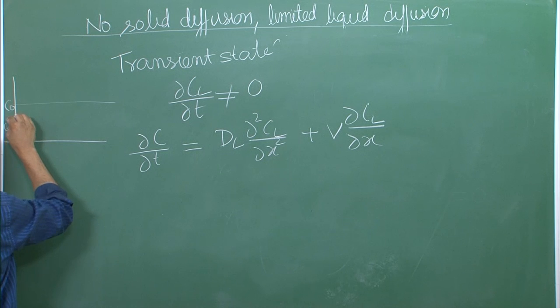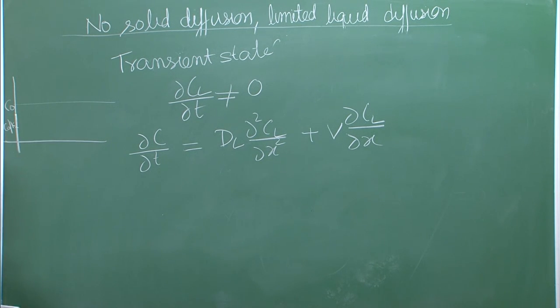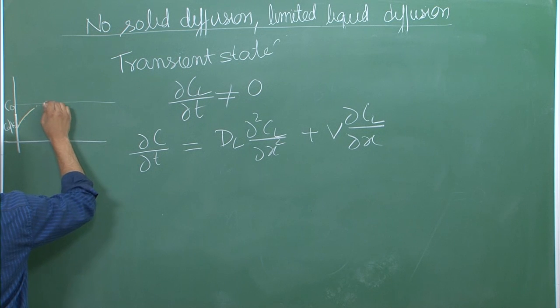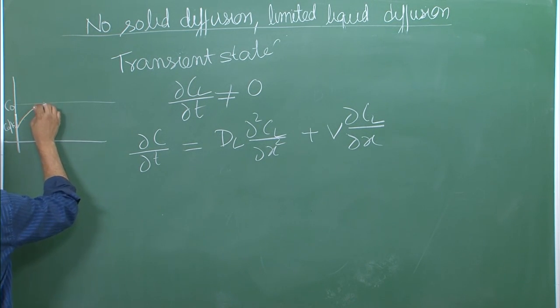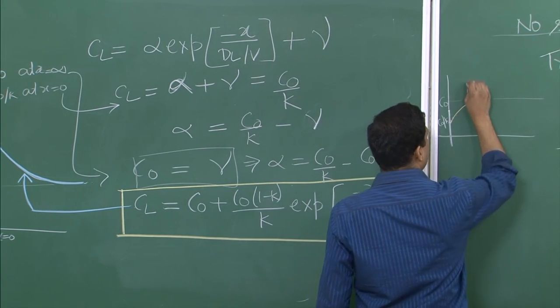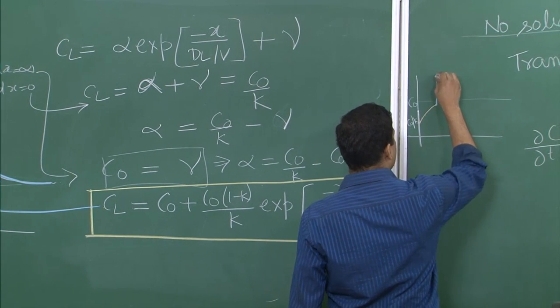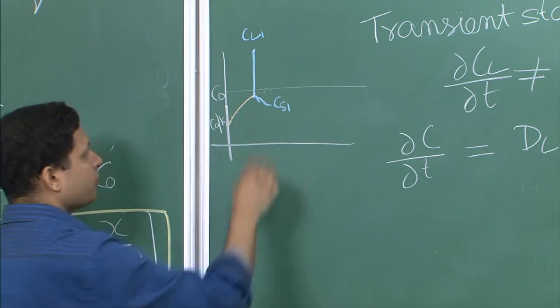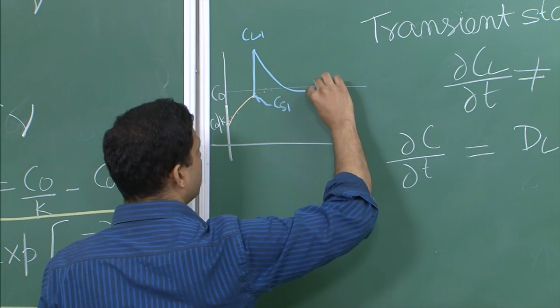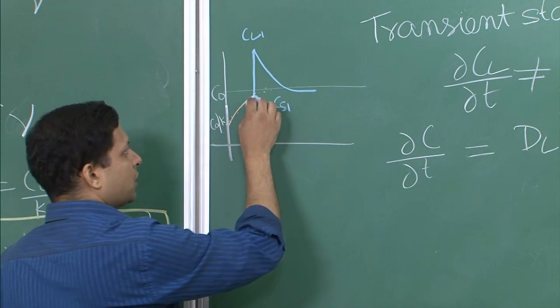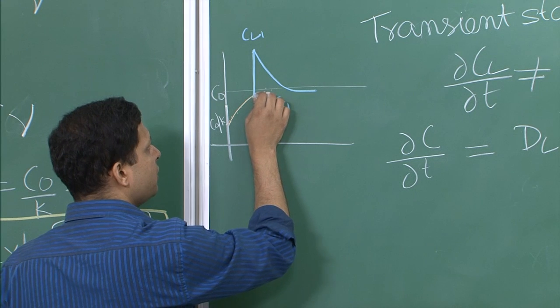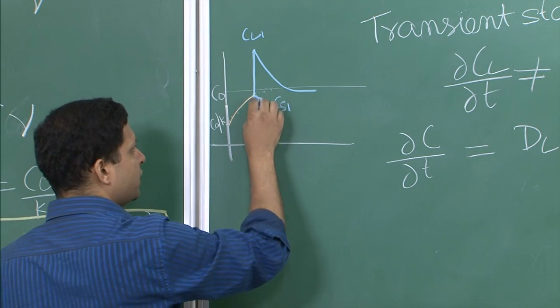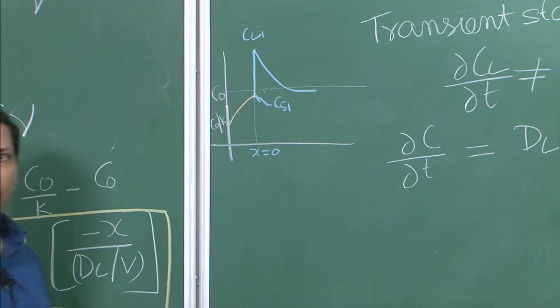This problem is very difficult to solve analytically. If we draw the transient condition: the overall concentration is C_naught; the solid that forms starts with C_naught/k. The liquid concentration profile decays from there, but its exact shape is not straightforward. As the solid concentration slowly reaches C_naught, the entire profile — including the liquid concentration at x equal to zero — changes continuously, which is why we call it the transient state.